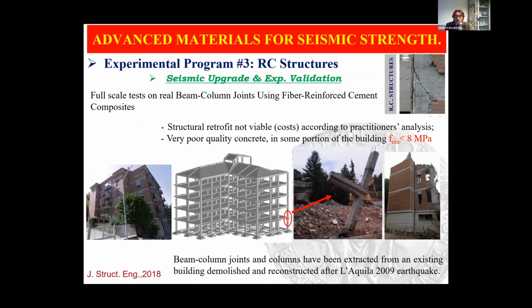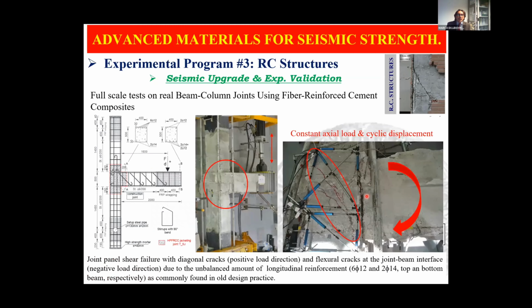And so what we did was to extract, during the demolition phases, some real beam column joints. We moved them to our lab, and here are the details of the specimen. We tested it in the as-built configuration, and as expected, the shear failure was achieved in the panel.